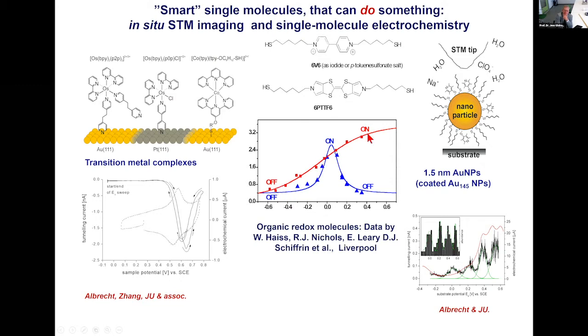And with Richard and his people, we wrote a theory of how one could interpret this as gated electron transfer. And this kind of tunneling spectroscopy even applies to nanoparticles, gold nanoparticles, if they are small enough. When the nanoparticles are small enough, they are no longer like small chunks of gold. They are like molecules that can be successively oxidized up to many different oxidation states. And this is shown here for a 1.5 nanometer gold nanoparticle. This is a differential pulse voltammogram, and this is in situ scanning tunneling microscopy directly in aqueous solution.